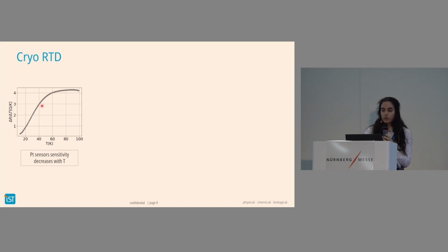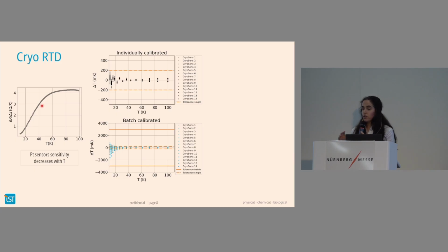However, what we also measured is that when we individually calibrate the sensors, the accuracy that they deliver is still quite good. So what you have in the upper plot are individually calibrated sensors. And what we are plotting here is the deviation of the temperature that they measure versus the temperature. So especially for temperatures above 20 Kelvin, one sees that this accuracy remains excellent and can be used quite precisely.